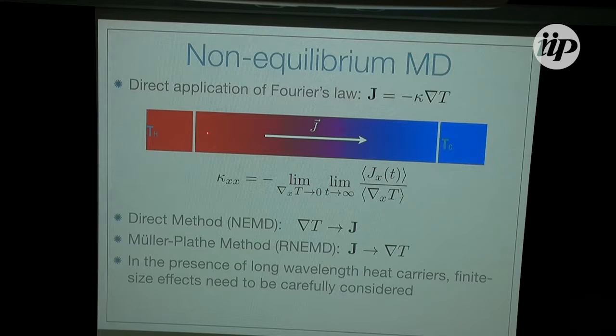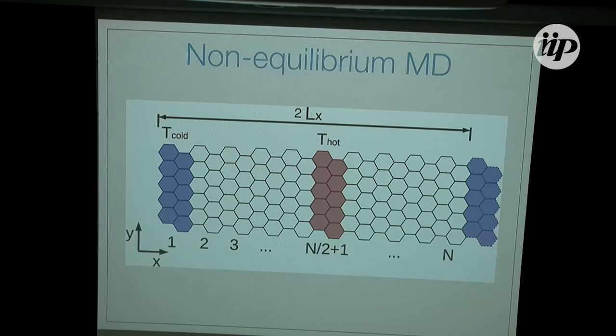What I want to do is start my simulation with a given size, and then keep increasing the size of that system until the thermal conductivity doesn't depend on size anymore. At least that's what we hope. In general, the inverse conductivity you calculate like this is the inverse of the intrinsic conductivity of the material plus a function that depends on the system size.